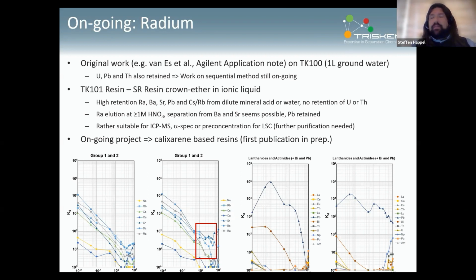There's still some work ongoing, as it retains quite large number of elements: radium, strontium, lead, thorium, uranium. So we still try to get a sequential method to get all of these from one sample. Looking not too bad, but still quite some work to be put in. And we do get limits on the type of samples that can be analyzed. There are interferences from matrix elements. So we switched a bit to TK101 resin, which is actually based on crown ether in ionic liquid.